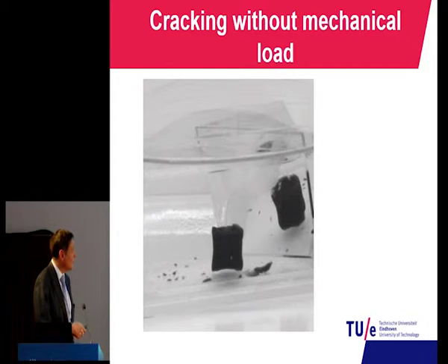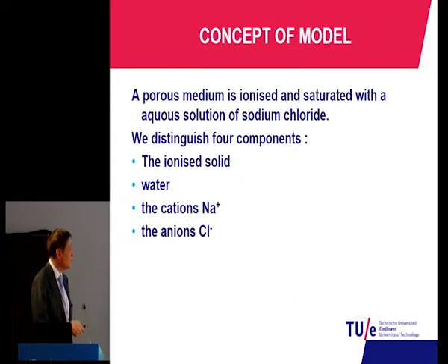So there is a curvature in this direction within the surface of the screen, and a curvature in the other, perpendicular direction, concave upward. This develops only because the inside doesn't swell as fast as the outside. During the swelling, water goes in, and at the same time there is a competition because ions want to go out. So two movements are going on at the same time, and different time constants play a role in this phenomenon.